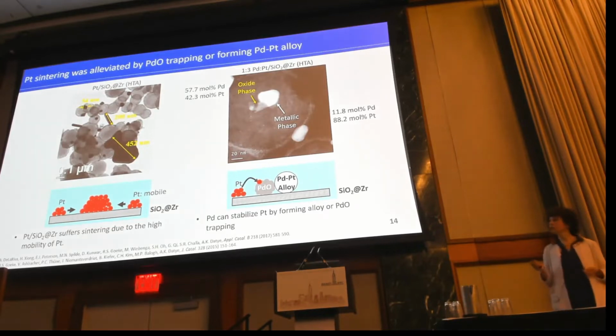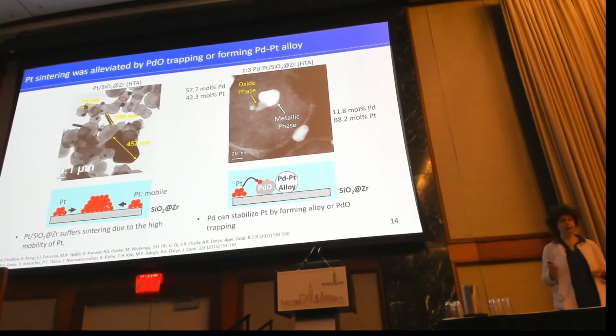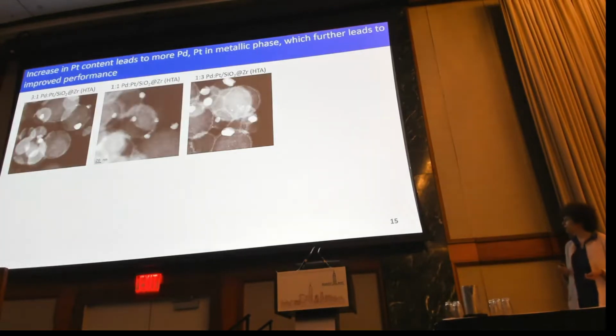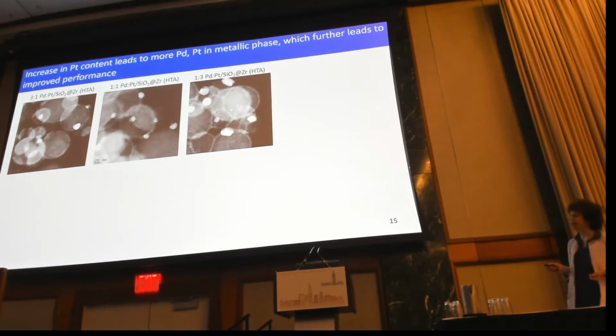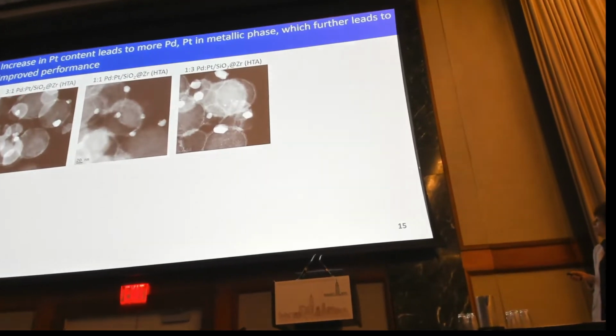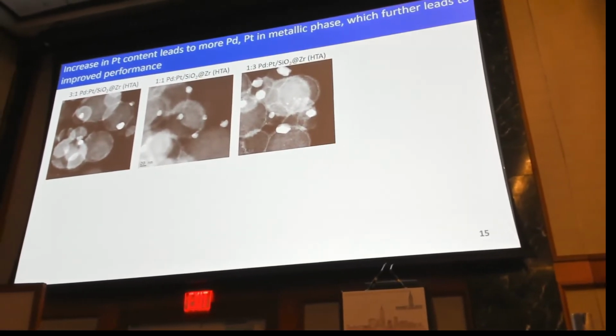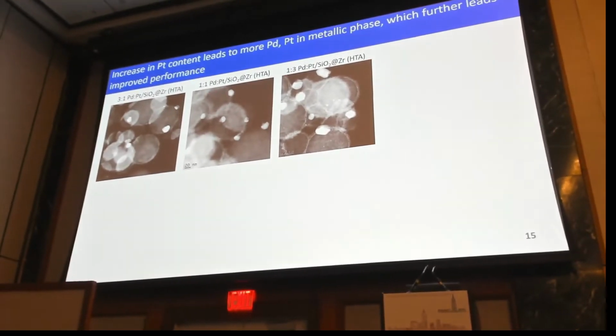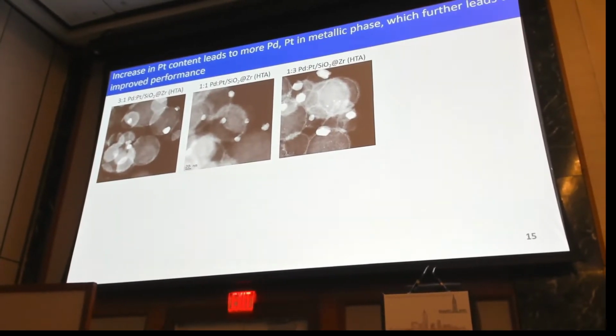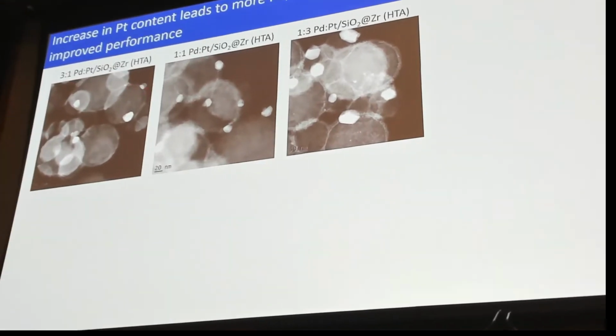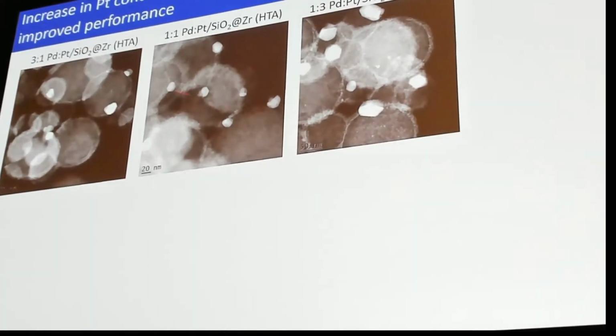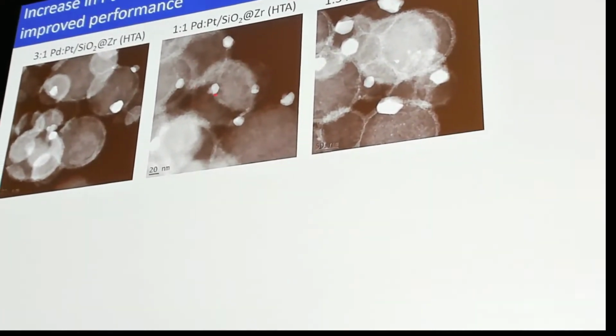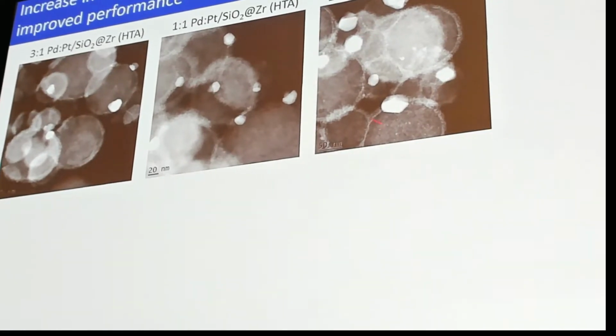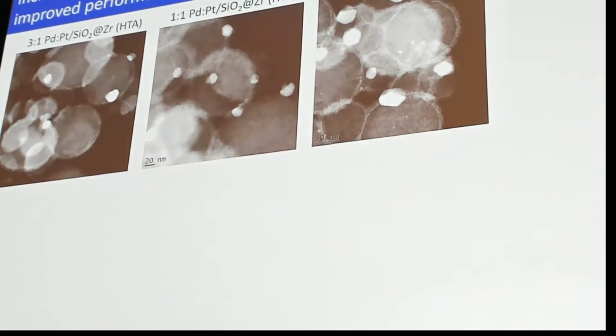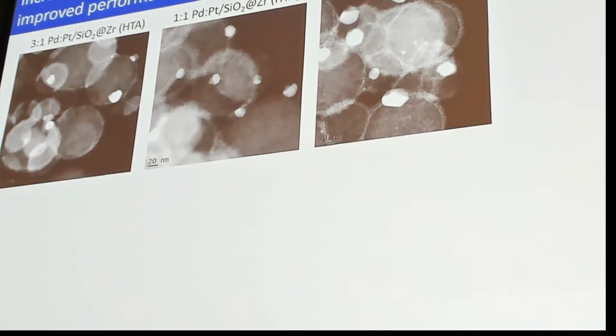So, in order to convince you that this is not the only biphasic particle we observe, I just want to show you a couple of images. So, these are images for the bimetallic catalysts after hydrothermal aging, with molar ratios of palladium to platinum of 3 to 1, 1 to 1, and 1 to 3. And as you can see here, we see a couple of biphasic particles. So this one, this is another one, here we have another one. So we have a couple of those biphasic particles.